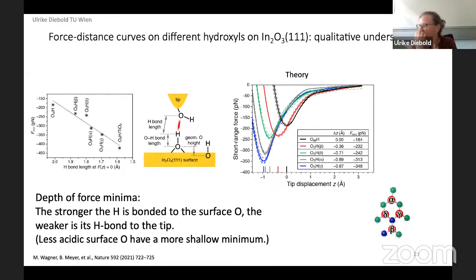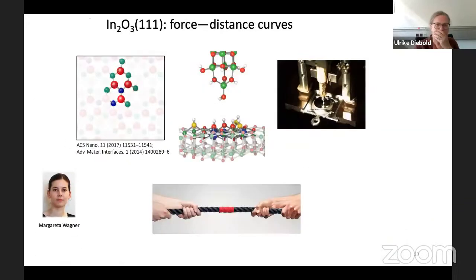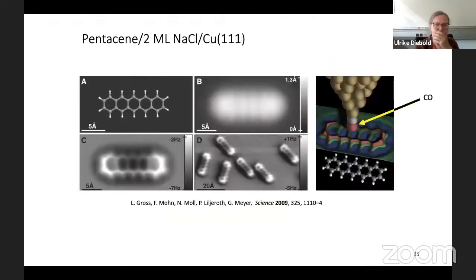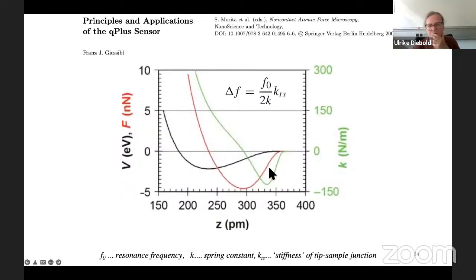Right, but you're pushing that bond sort of in. Yes, we go close enough, but we don't go beyond. That's how I showed this curve. We measure the green line, and then we integrate once and measure the red line. We're really not going closer than the equilibrium distance, because if we do, there is a real danger that we take this proton off the surface.